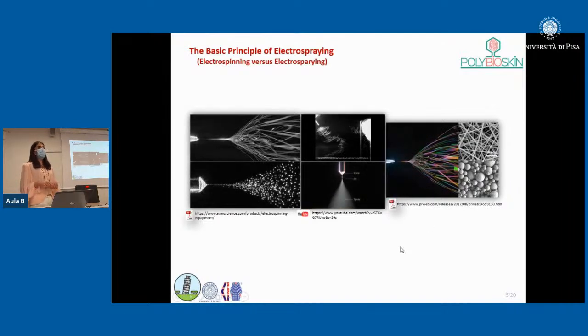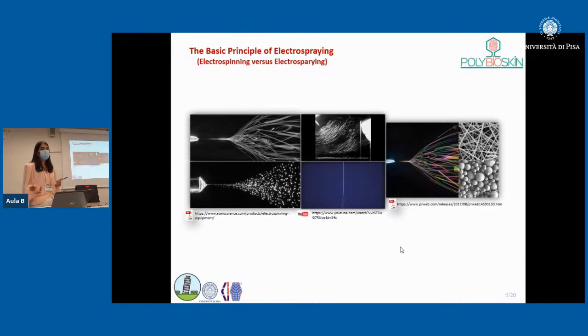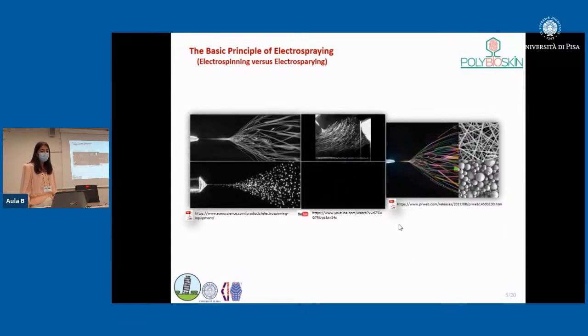So according to these results, we decided to use this kind of nanoscale natural biopolymers to functionalize the surface of different substrates. As I told you, for example, for Polybioskin, we decided to functionalize the surface of the electrospun nanofibers, polyhydroxyalkanoates, using electrospray technique. And as you know, this is one of the most important methods to produce nanofibers and nanoparticles.